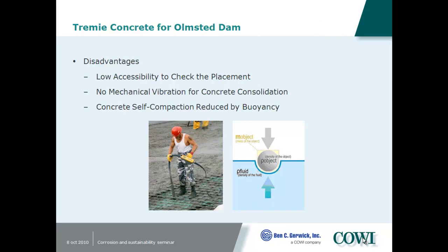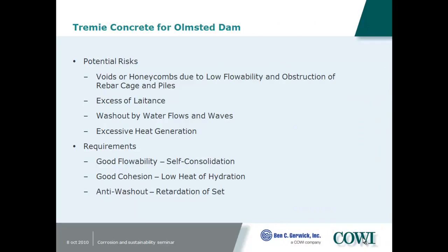Disadvantages: you have low accessibility to check the placement, so you need to do a lot of quality control in advance. There are sonic methods for checking, and coring and other methods. You don't normally consolidate the concrete. We've done studies where there are ways to consolidate it underwater, but if you start agitating, it can promote mixing with the water. You want something that's self-compacting, but of course with buoyancy, it doesn't flow out the same way because it's supported by the water.